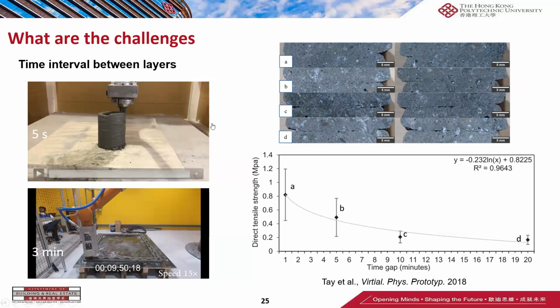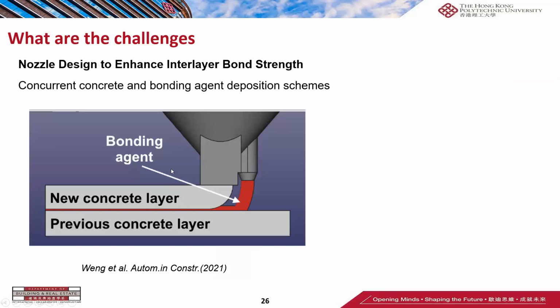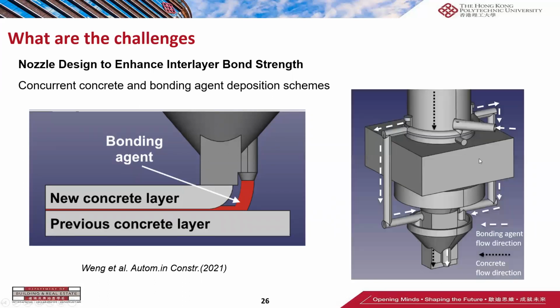To address the interface issue, we further designed a nozzle system which can deposit a bonding agent between the interfaces. Then the bonding agent can help to enhance the bond performance of the final printed structure. This kind of printing scheme, we call the concurrent concrete and bonding agent deposition scheme. This is the design prototype of the nozzle system. You can find that for this nozzle, we have 2 flow channels. One is for the concrete flow process, and the other one is for the bonding agent flow process.